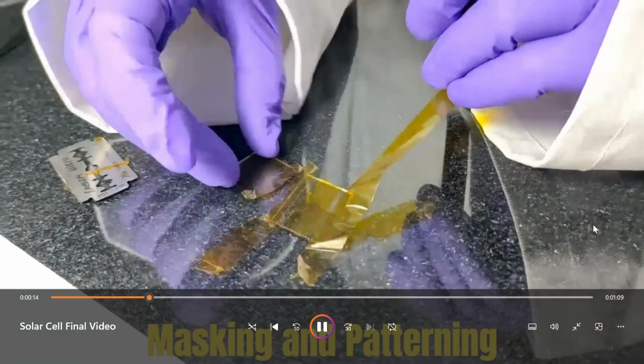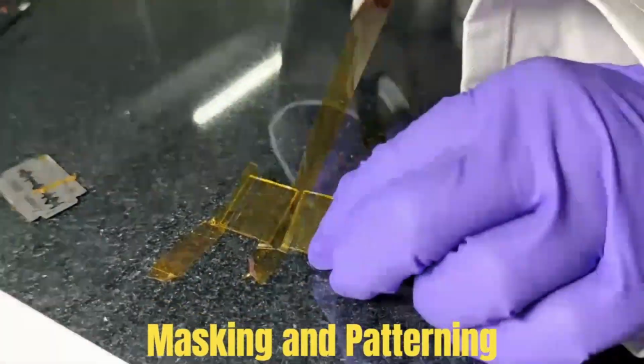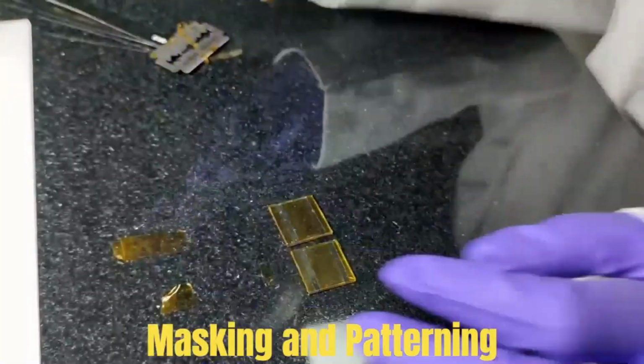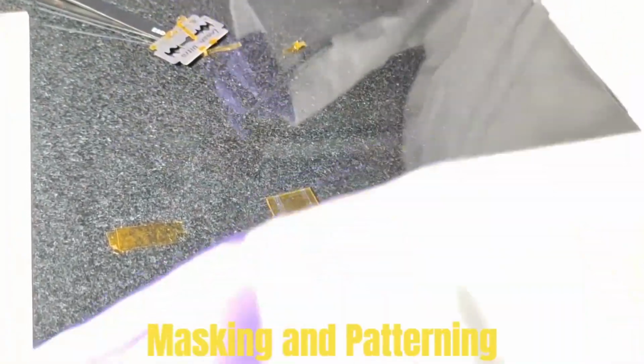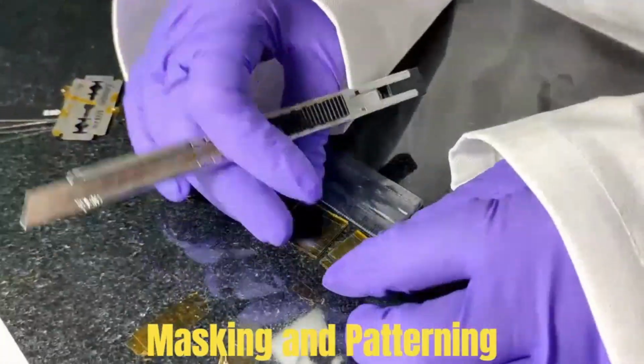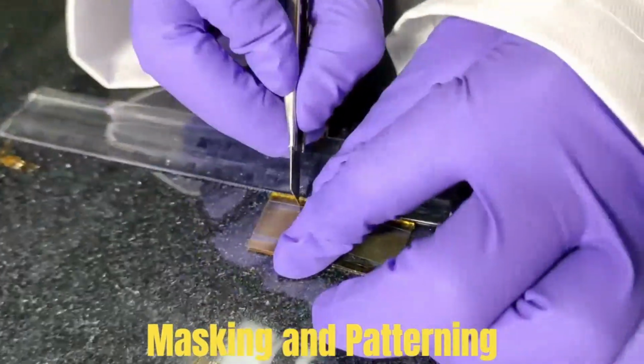After masking and patterning, we cut it and clean it. You have to clean the FTO first in isopropanol and ozone, then heat it, and then do selective patterning.